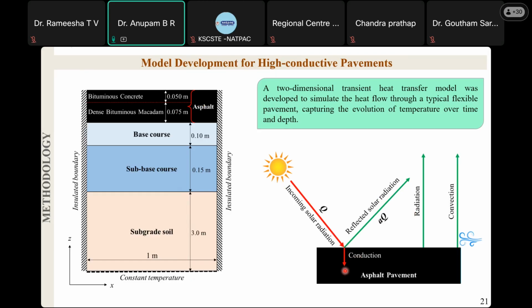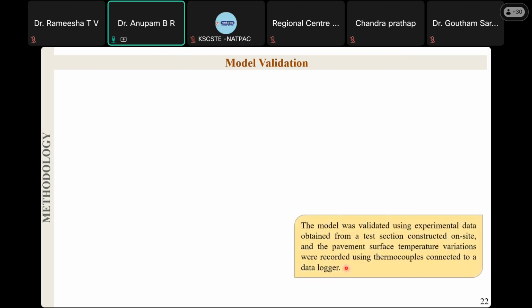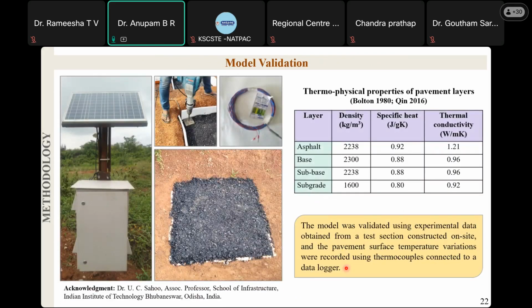And for various thermal conductivities, we changed the conductivity of this material in the range that we can achieve by adding some materials. And we see how the temperature of these materials varies under solar radiation on a typical day, how the pavement surface temperature is varying. Meaning if we increase the thermal conductivity, are we really achieving the reduction in pavement temperature? That also we have done. And we have validated the model using experimental results. We cast asphalt pavement test slabs with the exact dimensions that we considered in the model, and we collected experimental data using thermocouples and a data logger system. And we validated the model. We validated our data with the experimental and numerical model.